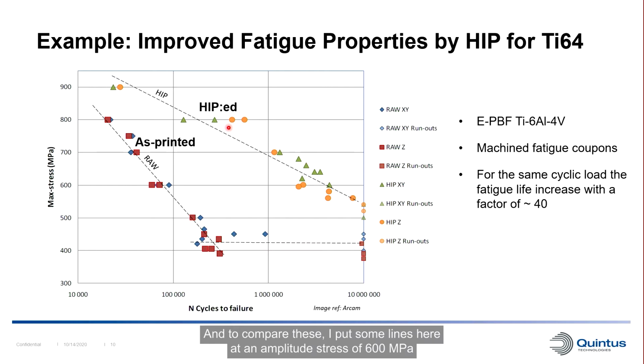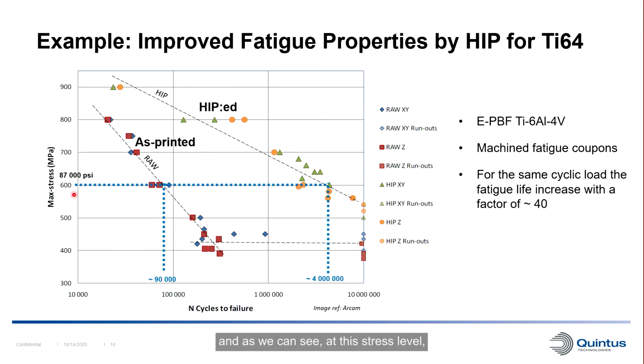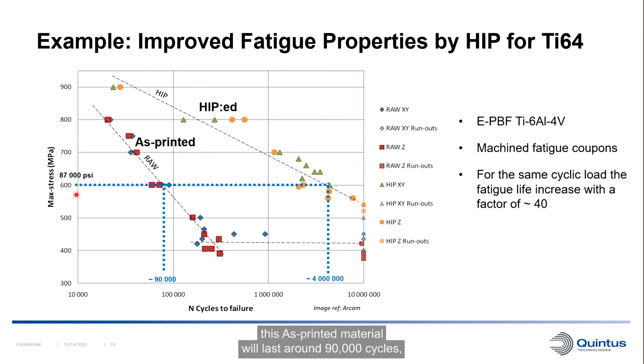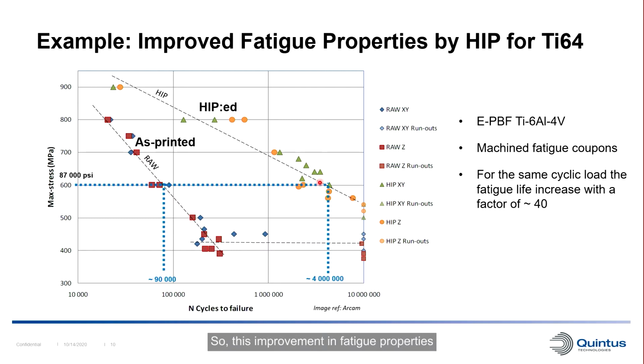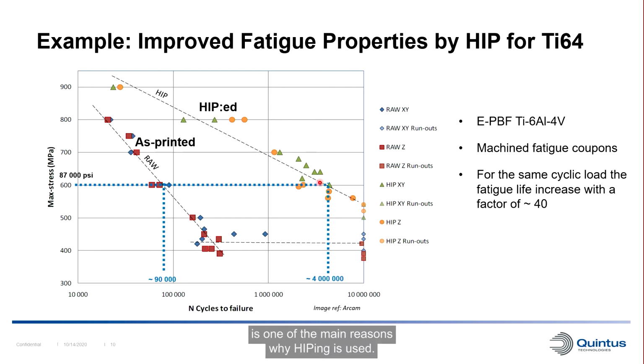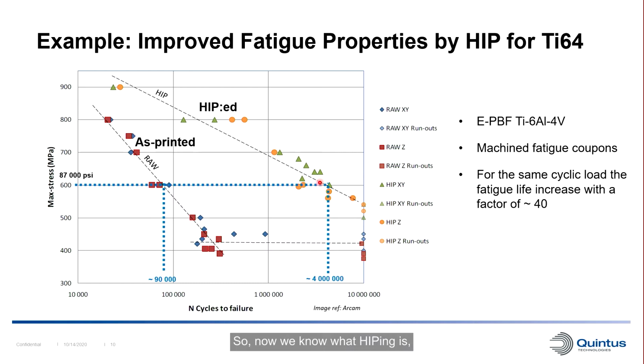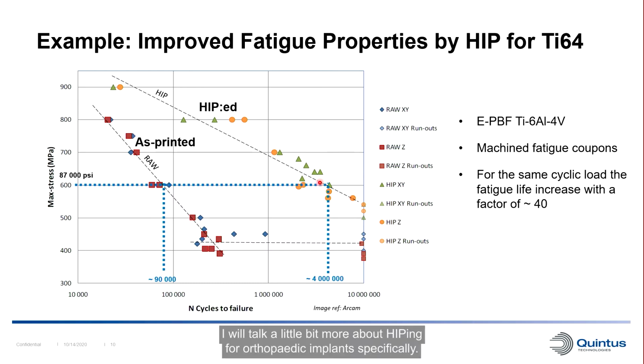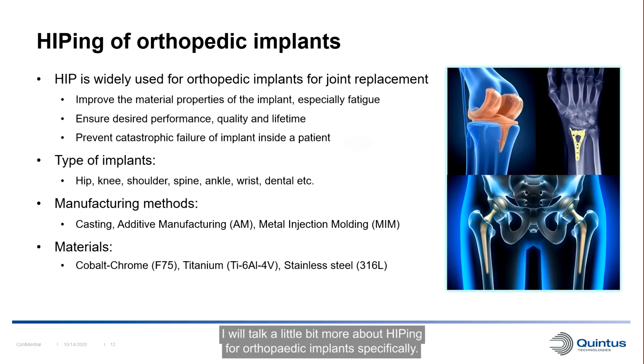And to compare these, I put some lines here at an amplitude stress of 600 megapascal. And as we can see at this stress level, this as printed material will last around 90,000 cycles. But with the HIP material, we get around 4 million cycles at the same stress level. So this improvement in fatigue properties is one of the main reasons why hipping is used. So now we know what hipping is, then I will talk a little bit more about hipping for orthopedic implants